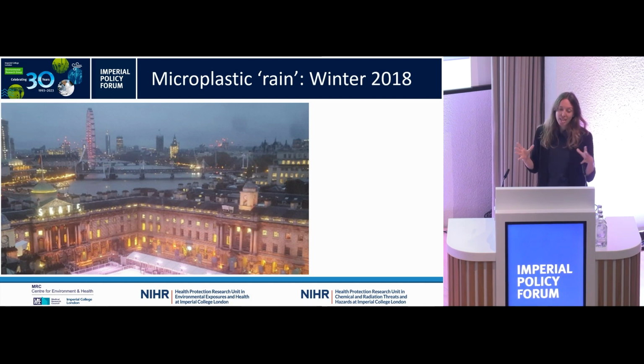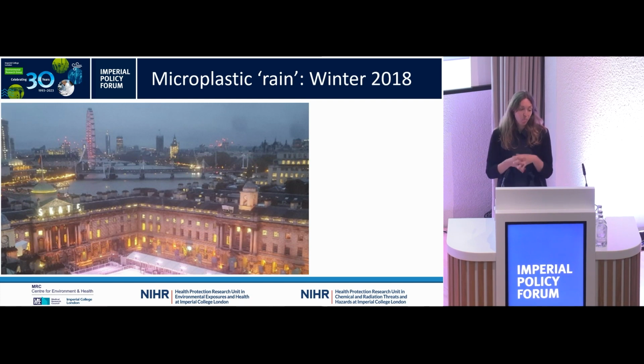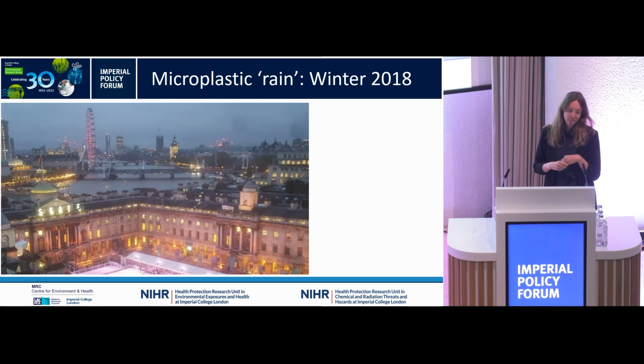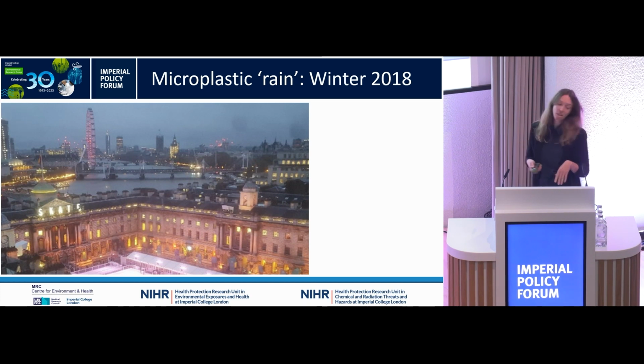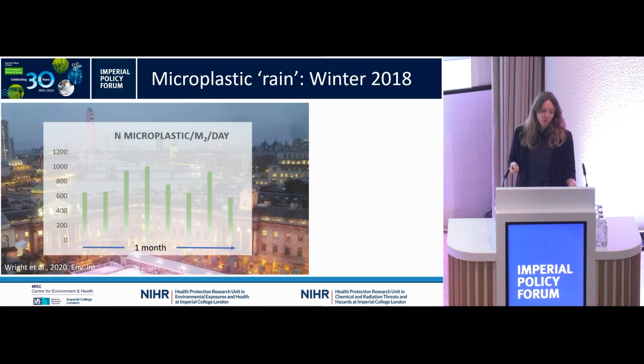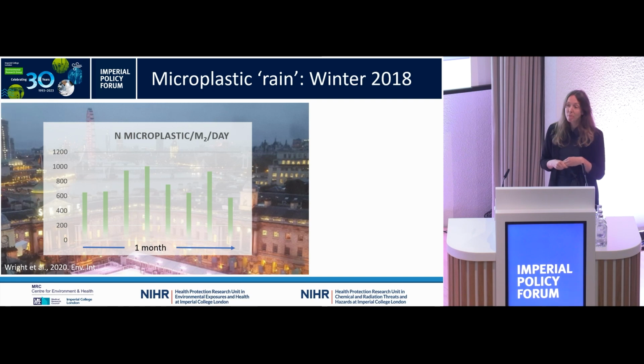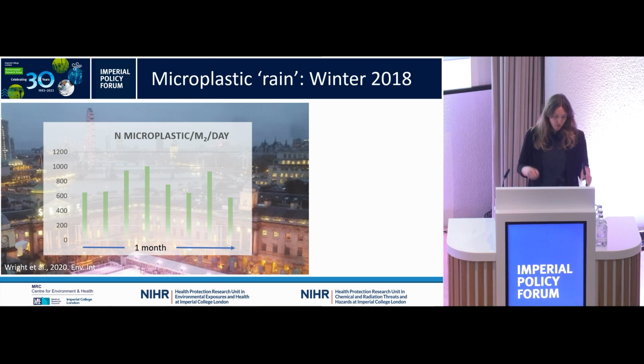Those were the overlaps. And obviously surrounded by the amazing research going on in the team, I quickly became interested in whether this material was airborne as well. So the first challenge was to figure out, are they in the air? We did some sampling on a rooftop in central London. We were then at King's College, on the Strand campus with a very nice view. Over the course of a month, as we sampled the atmospheric deposition settling naturally out of the atmosphere, we found microplastic contaminated every single sample. And this is 50 meters high off the ground.